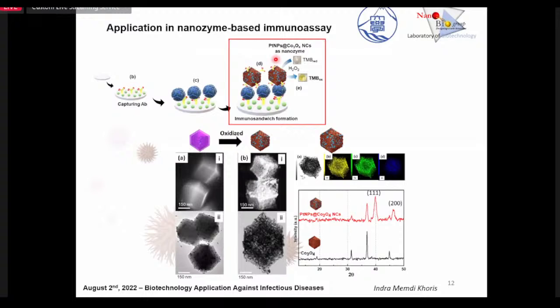Proceeding, we also would like to introduce the second heterostructure. Similarly, after the immuno sandwich formation with our heterostructure nanoenzymes, it will exhibit a color change when we introduce our substrates, showing the detection of the virus based on the color. Beautifully, on the TEM analysis, we can see the oxidized nanocage, showing a porous, semi-porous, or what we call pseudo-porous nanocage with integrated platinum within the structure.